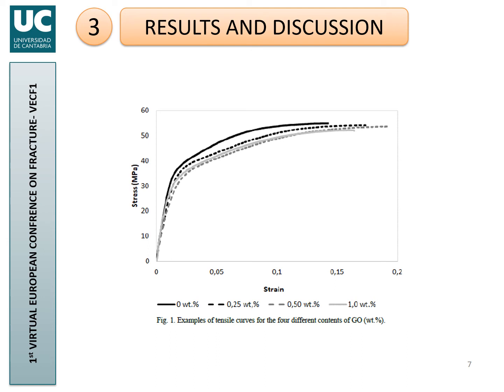So, which are the results that we have obtained? Here you have the tensile tests. You see that the upper curve corresponds to pure polyamide. So it is quite clear that graphene oxide does not improve the strength of the material. When we have introduced nanoparticles on PA6, the Young modulus has become lower generally, and the yield stress and the ultimate tensile strength have been also lowered.